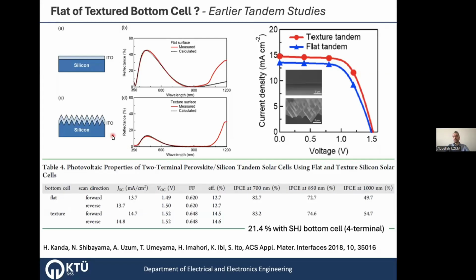You will see in coming slides that actually this is not applicable for monolithic tandem structures, because in the monolithic tandem structures, you need to fabricate your cell above these layers, right? The top cell. But when it is textured, you will see that perovskite materials cannot form on the textured surface very efficiently. That's why, as I will mention when it comes, they make the surface flat and then continue to fabricate the solar cell on a flat surface.